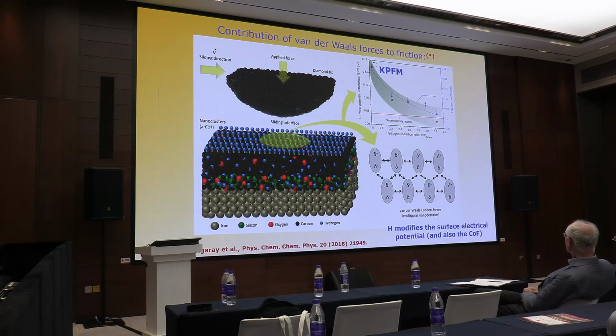Good. Okay, in this case, we interpret or discuss the result with van der Waals forces between the surface of the sample and the tip. Also, this is very clear, the hydrogen modifies the surface electrical potential. You have the coefficient here. When you have more hydrogen, the potential of the surface is lower, or the surface cannot accumulate too many tribocharges. This is the meaning in practical terms.